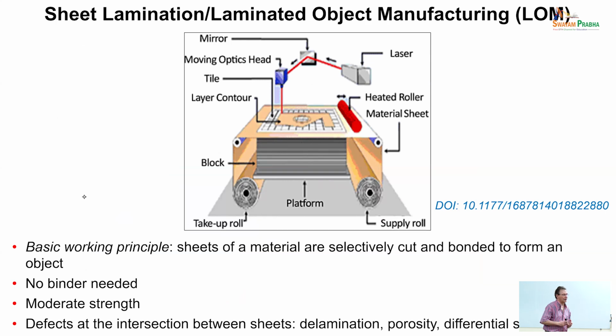So LOM, laminated object manufacturing. And this is not really a 3D approach, it's more a 2.5D approach. Basically, you have sheets of your material, and then you inscribe them, typically using a laser, and then you need to bind the layers together. And this can be done with sheets containing ceramic particles. It has been done with sheets containing particles, but this is not a technology that people actually use a lot for making 3D parts. And you have issues in terms of defects at the intersection between the different sheets.